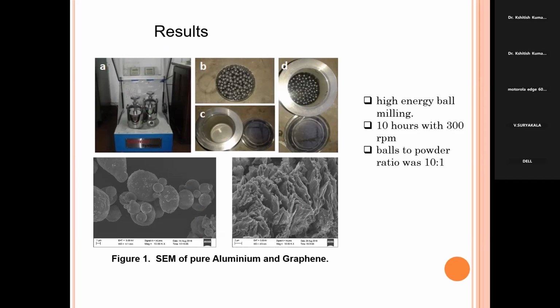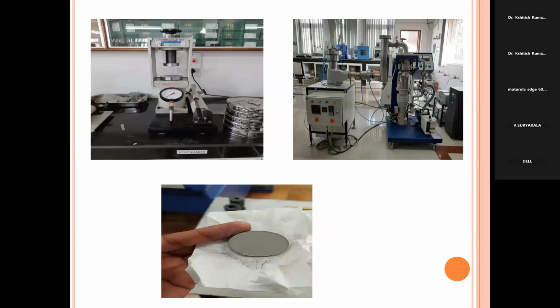Before conducting the SEM experiment, we have taken the SEM graphs, and this is the weight machine. And in the second figure, after preparing the pellets, we have sintered them in that vacuum furnace. Whenever we prepared the ferroelectric material, we used a high temperature furnace, and that is not vacuum. But when we prepared the aluminum metal matrix composite, we took a vacuum furnace, because if we do not use a vacuum furnace, an aluminum oxide layer is formed. So for getting pure aluminum, we have taken the vacuum furnace. And the third one is the pellet, that I have already told you about.